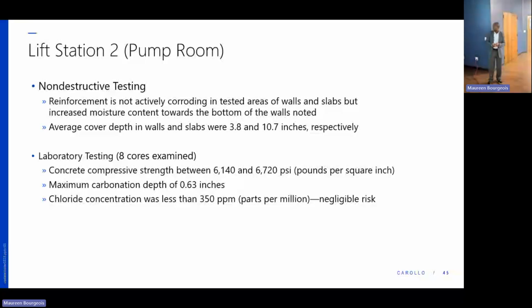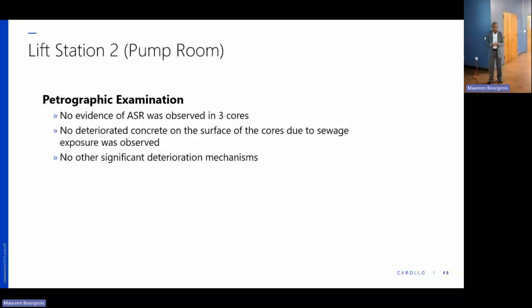So again, petrographic examination, looking under the microscope, what do we see? No ASR was observed in the 3 cores that were tested. Concrete here, no deterioration, that's the dry portion, and there are no other mechanisms for cracks that we saw in this segment.